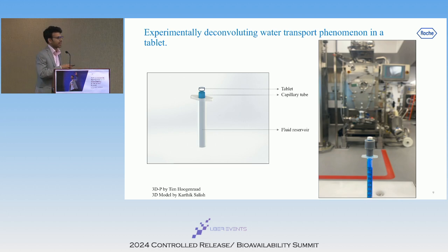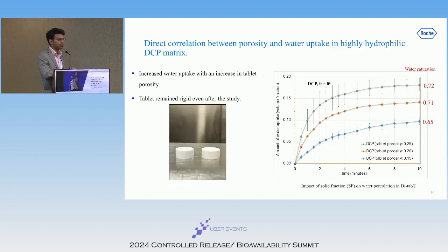Okay, great, thanks. The capillary tube helps convey water that is present in the fluid reservoir into the tablet, and the water uptake can be measured using an analytical scale at predetermined time intervals. We added trace amounts of blue dye to help better visualization. After having the method ready, we evaluated the pure DCP and MCC tablets.